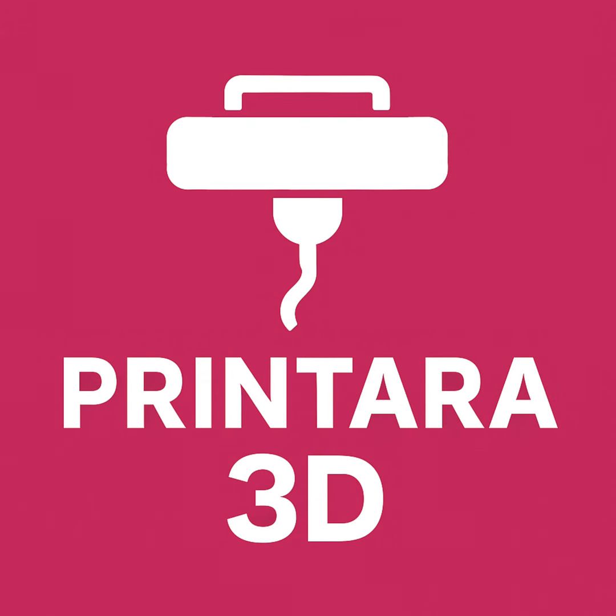Precisely. Hydrolysis chemically severs the long polymer chains of the plastic. It breaks them down into much shorter chains. And the entire mechanical strength of these materials relies on those long, entangled chains, right? Exactly. When you break them, you permanently degrade the plastic. If you print wet nylon or PC, it really does not matter how well the part looks on the outside. Because the chemical structure has been compromised? Yes. The mechanical properties we just discussed will be gone. The part will be dangerously brittle.